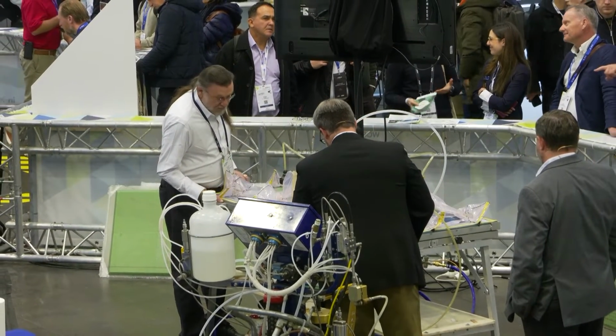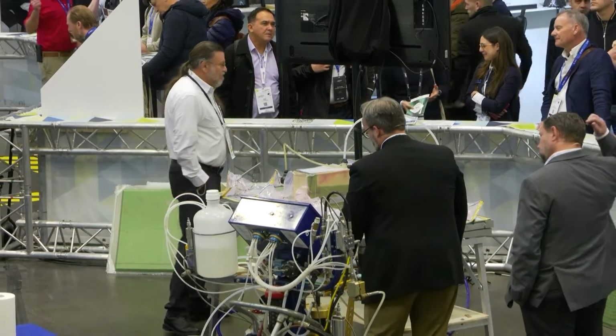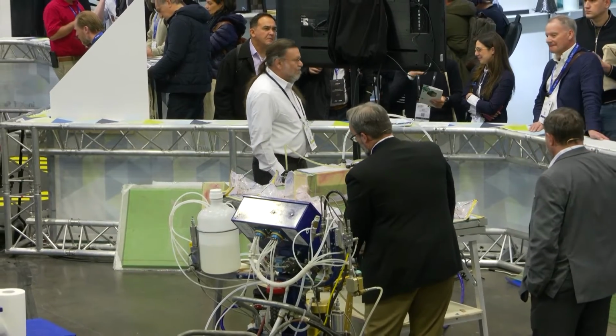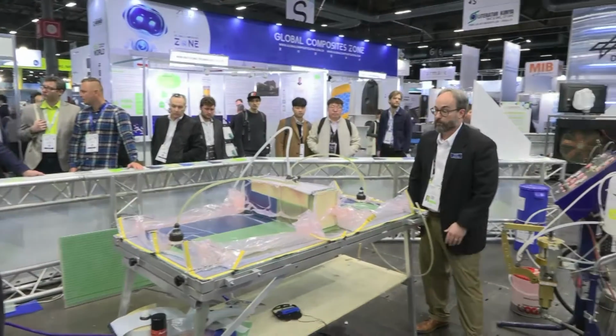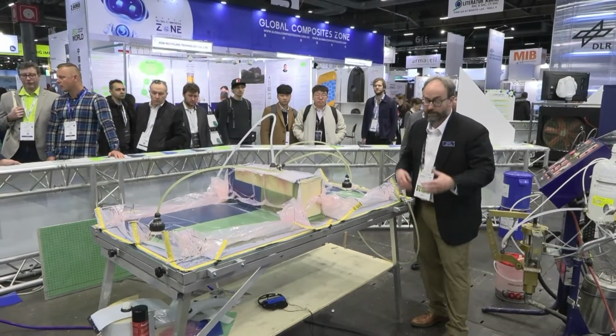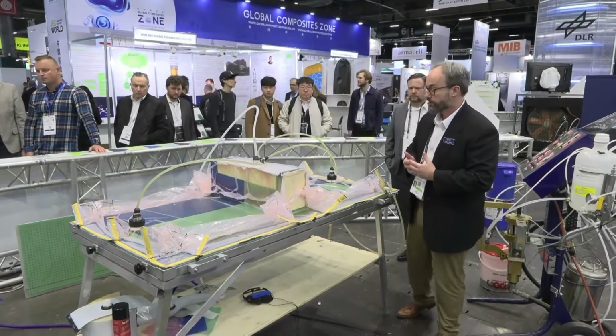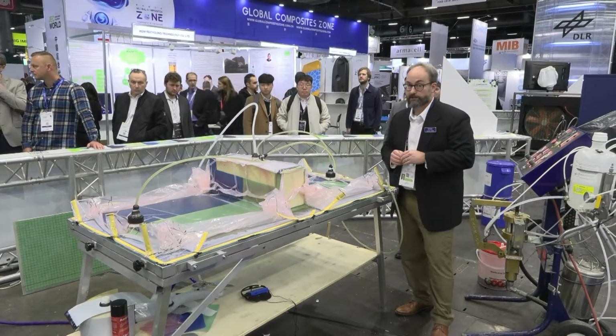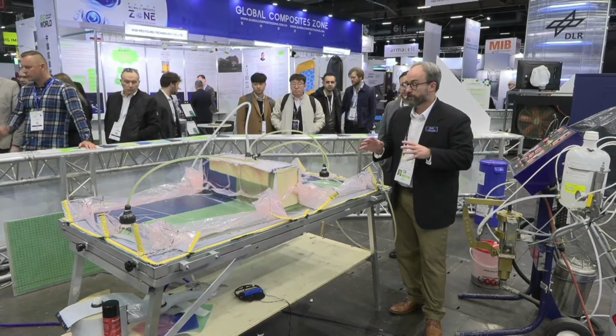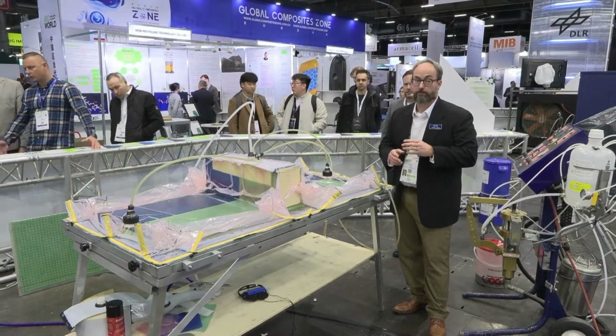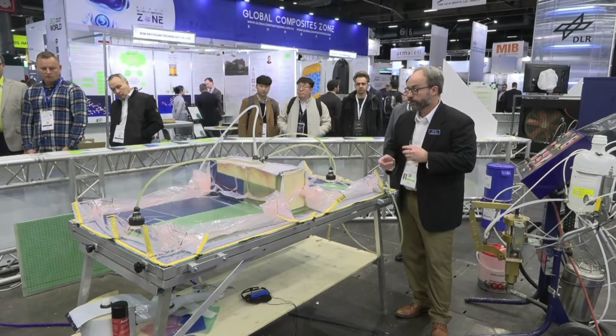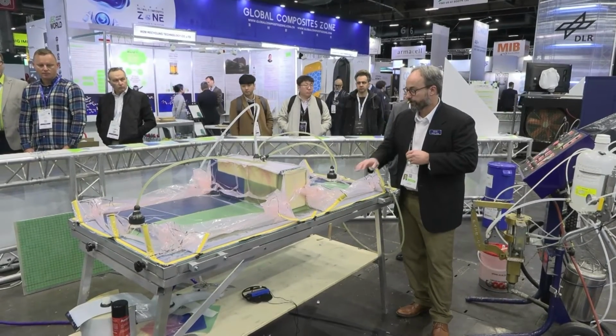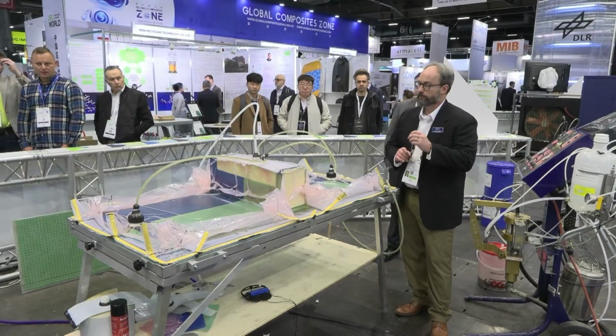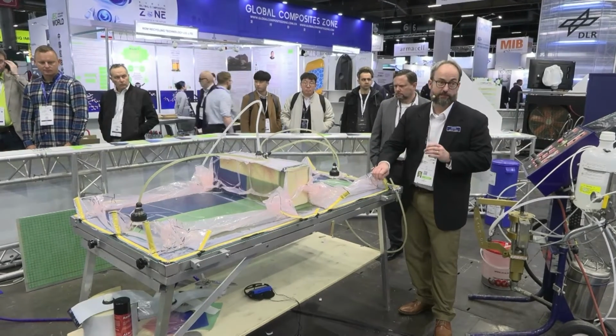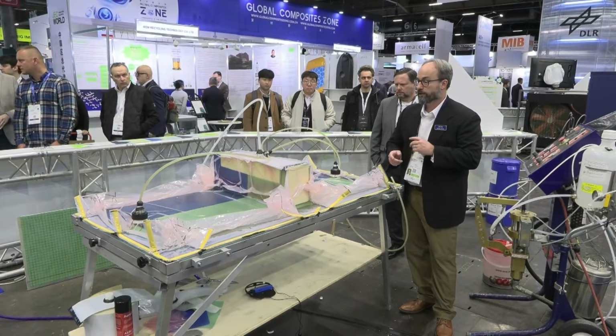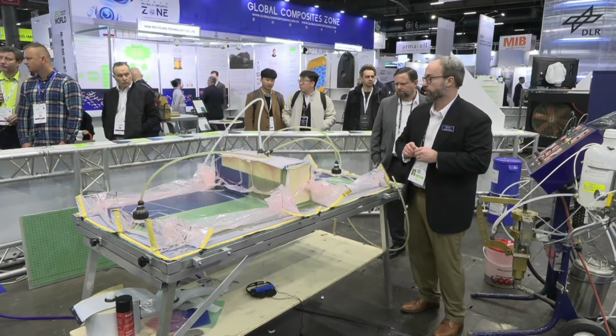As I mentioned, we can get fiber volume fractions approaching 50%. Fiber weight fraction for fiberglass is in the range of 70%. And very low porosity. Since everything's under vacuum, we have plenty of time. We're not relying on the gel time of the resin. We can make sure that our vacuum bag is sealed perfectly before we ever mix the resin or start the injection process.